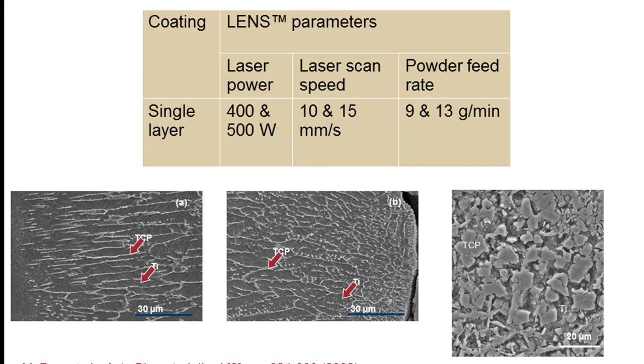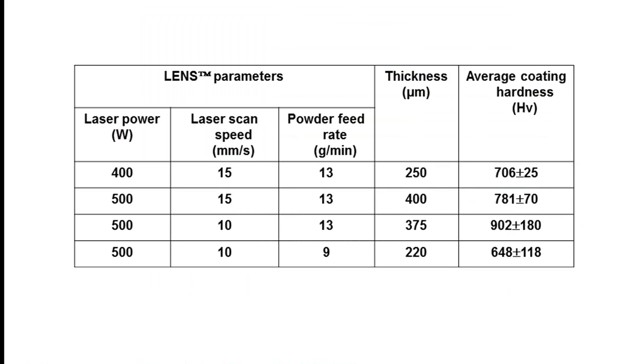We can actually make it. If you look at the properties, depending on the laser power, we can change not only the thickness of the coating but also the hardness of the coating and so on. So we can play with these basic LENS parameters and show that you can vary the coating properties depending on hardness, biocompatibility, or whatever you want.